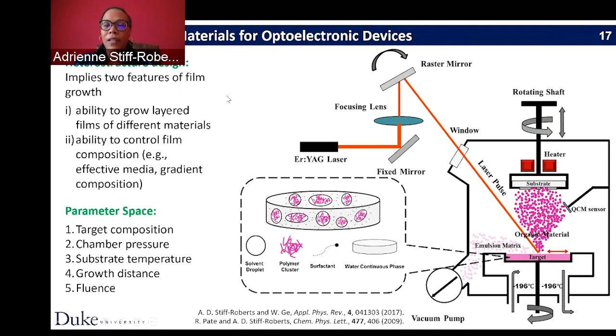So things that are done all the time in a system like MBE, molecular beam epitaxy, but is extremely difficult to achieve when you move to polymer systems that are typically deposited using solutions. So one is just the ability to grow layered films of different materials. Having one layer that's one material, a second layer that's a different material. That's been a challenge for polymer films because they typically have the same solubility. So if you put down one layer and then go to the second layer, you'll destroy the layer underneath because they're soluble in the same solvent.